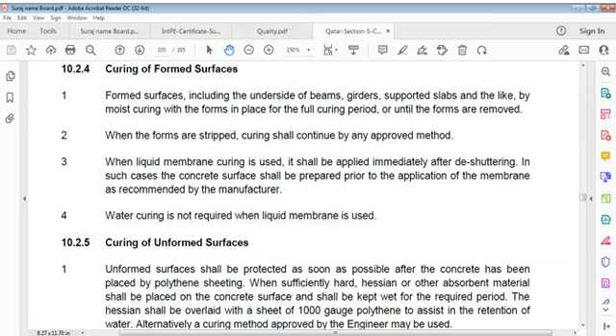I think water-based doesn't exceed 60 to 70% effect, whereas wax-based is fully effective. But the problem lies in that if you apply wax-based, this membrane shall be there for at least, it takes probably 6 months for degradation of that, and maybe you don't have time of 6 months to wait for another application on concrete surface.